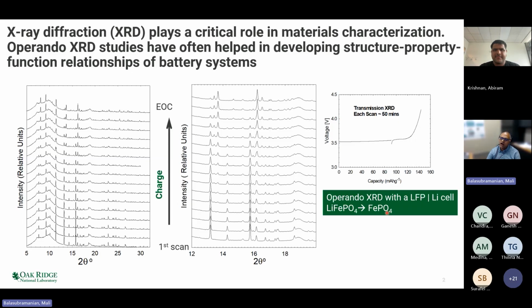So nowadays, X-ray diffraction can be done relatively fast at a synchrotron. You can get high quality spectra in sub-second like timescales. So one should be able to understand or study things like dynamics of electrodes during a pulse charge or a pulse discharge, for example. So you can really collect X-ray diffraction at a very fast rate, and so you can follow things that happen in batteries very well.